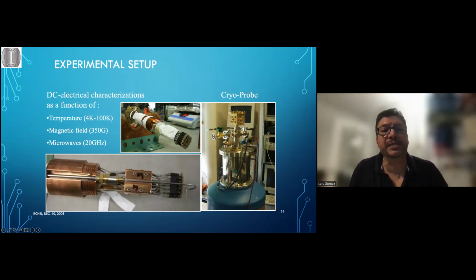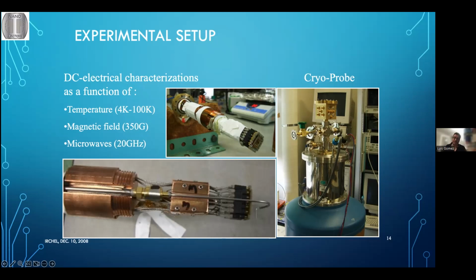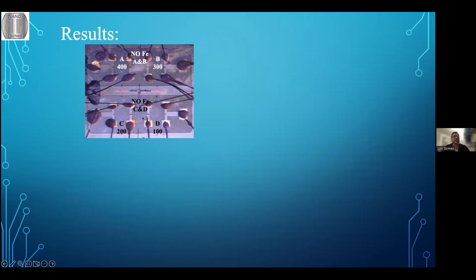And then we have, on each side, about 5 electrodes. So we can measure a total of 20, have 20 different leads that could go to a complex circuit. So this was one of the first samples that we made. Basically, it is a high temperature superconducting film. And well, you don't see it here very well, but I would make bridges of different width. So the number here will be the width of the bridge in nanometers. So this is 400 nanometers.